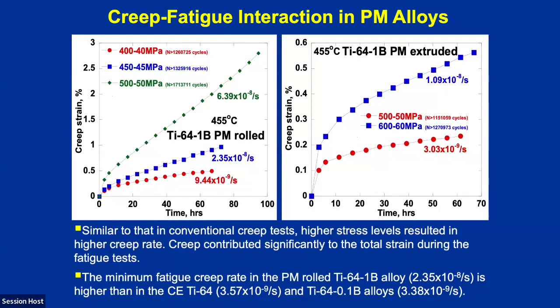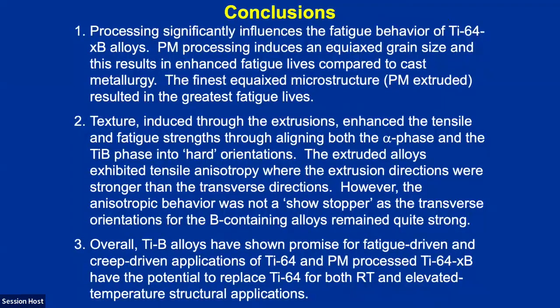And so to conclude, processing significantly influenced the fatigue behavior of Ti-6-4, where the PM processing induced what we call an equiaxed grain size that results in enhanced fatigue lives compared to the cast metallurgy. The finest equiaxed microstructure resulted in the greatest fatigue lives. And the texture induced through the extrusions enhanced the tensile and fatigue strengths by aligning the alpha phase and the TiB phase in what are called hard orientations that we're not going to see slip happening as much in. The extruded alloys exhibited tensile anisotropy, where the extrusion directions were stronger than the transverse orientations, and they were also less ductile than the transverse orientations.